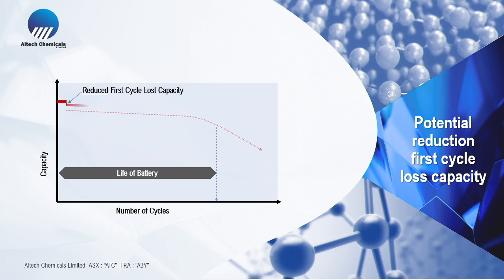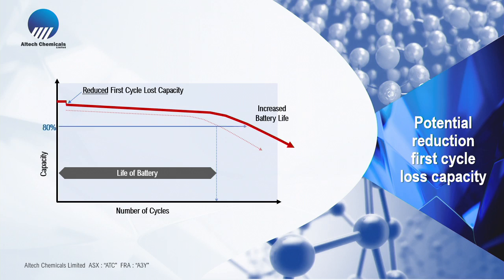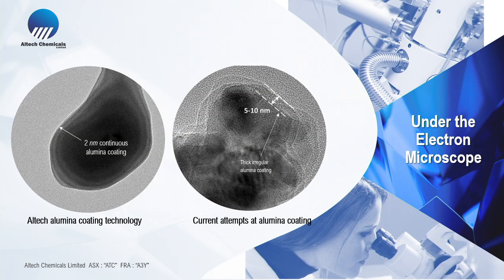Very reduced first cycle loss, and the curve stretches out. At the 80% level, that's the life of the battery. So we expect an extension of life of the battery just from coating the graphite particle with alumina. We are well in our test work, and if you look under the microscope, very strong microscope, the right-hand side is what conventional people are doing.